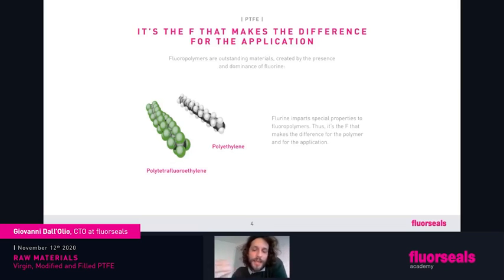It means that polyethylene has a lower chemical resistance, for example, because if something is going to attack these two chains on the polyethylene, carbon has a quite weak bond with hydrogen, and they want to do bonding with other stuff. On polytetrafluoroethylene, PTFE, as you can see, we have fluorine atoms that are protecting the carbon backbone, and then the strong bond between carbon and fluorine. This is everything related to the properties of PTFE. We will see more in detail about this, but remember, this strong bond between fluorine and carbon and the big atoms of fluorine that protect the carbon is what leads to the performance of PTFE.